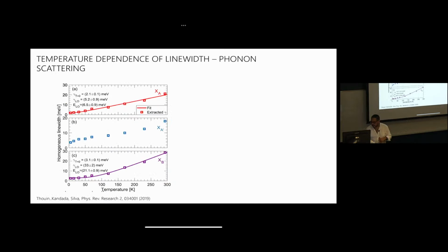So now I'm going to wrap it up. You can also do temperature dependence. And again, the temperature dependence is different for XA and XB. What is the thermal dephasing mechanism for your excitons? Your excitons have this mesoscopic phase, but now they couple to phonons. There's this exciton that couples to a phonon at a different point in the period to this other exciton. That's a dephasing mechanism. And so as you populate phonons with temperature, you would expect a thermal dephasing, and you see that that's different for XA and XB.